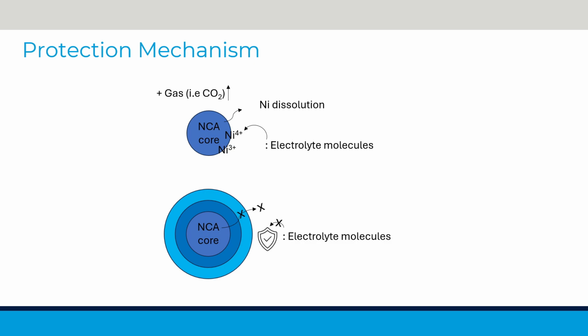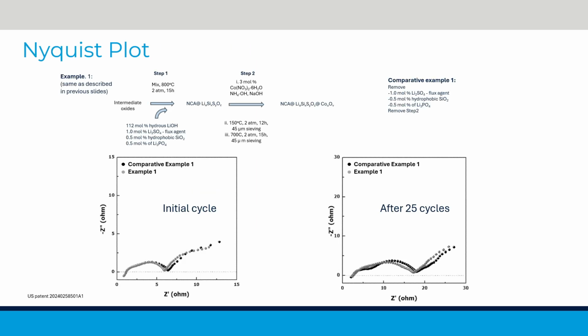The protective layers prevent nickel from being attacked by harmful substances. Moreover, the highly oxidative species, such as nickel 4+, is isolated so it cannot oxidize electrolyte in contact. These all contribute to a longer cycle life of the cell. The authors reported results from very systematic comparison among particles prepared in different ways.